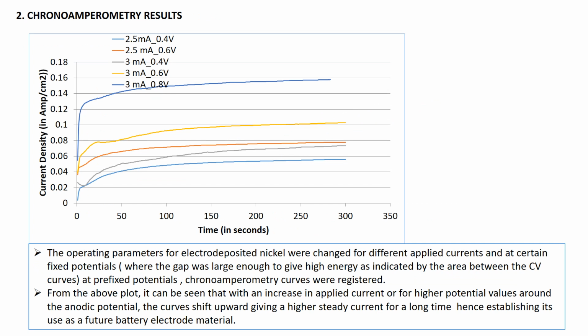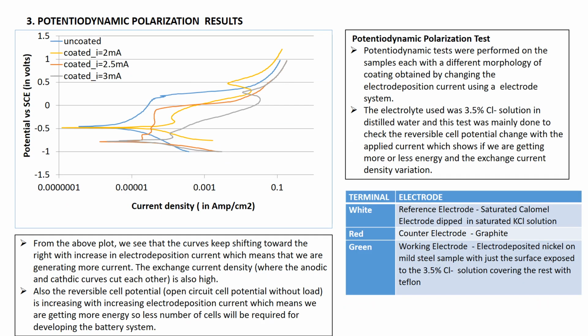Then the chronoamperometry results. The operating parameters were changed here also at prefixed potentials, and at certain fixed potential values these curves were registered. From this curve we can see that with an increase in applied current, or for higher potential values, the curves shift upward, giving a higher steady current for a long time, establishing it as a future battery electrode material.